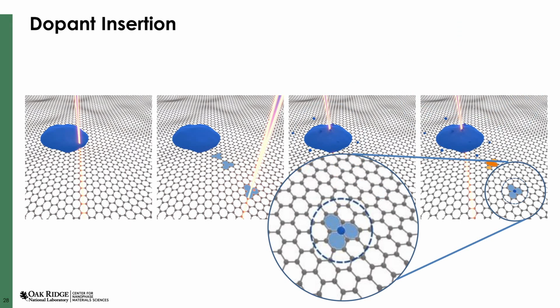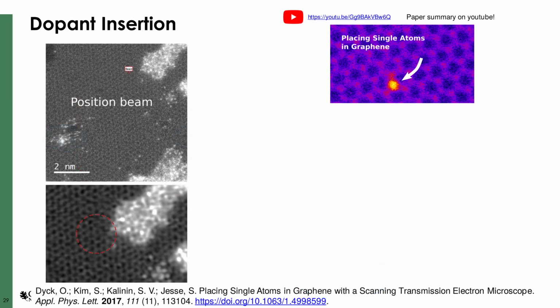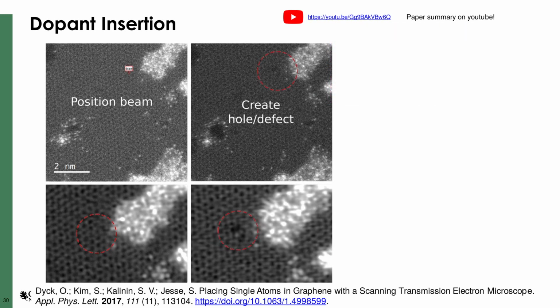It sounds plausible, and there are compelling drawings, but talk is cheap. Does it really work in practice? The answer is yes. Here are images of the first demonstration published in 2017. This is a single layer of graphene with some contamination on the surface, the bright areas. In the contamination, we almost always find some silicon atoms. The beam was positioned about a nanometer away from the contamination and a small hole or defect was formed.